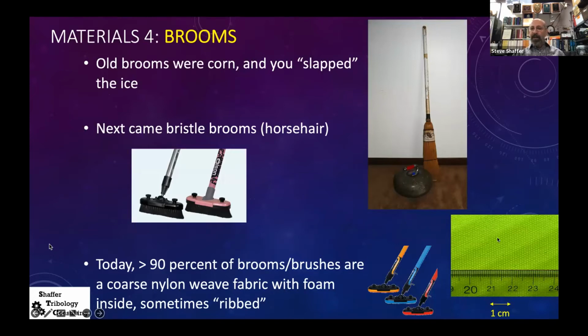And here's a high mag photo of one of these pads. You can see the ribs here. You can see that the asperities of the nylon weave are on the order of 1/2 to 1 millimeter or so in one direction, and maybe 1 millimeter or so to 2 in the other direction. So that's the modern curling brush.